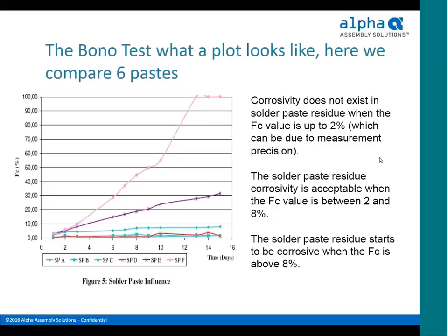However, all that said, what you see here is a low value is good. Anything below 2% is considered to be within the margin of error of the test measurement. Up to about 8% is considered acceptable per this test. Above 8% is where there gets to be a concern about the corrosive nature of that residue.